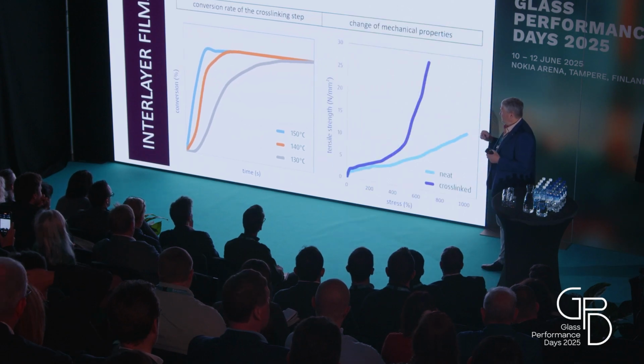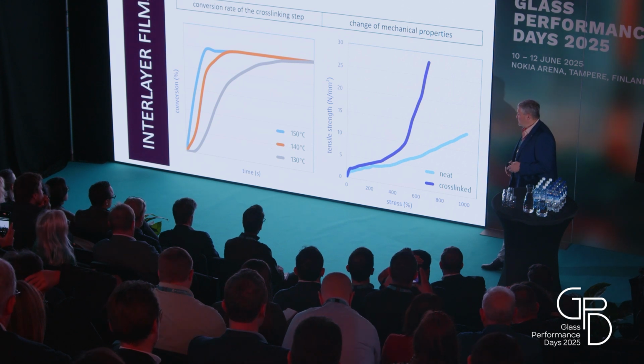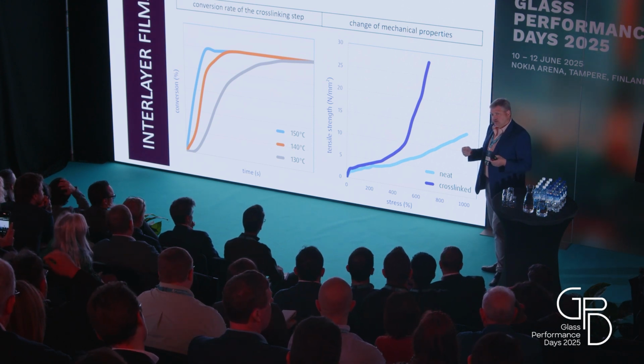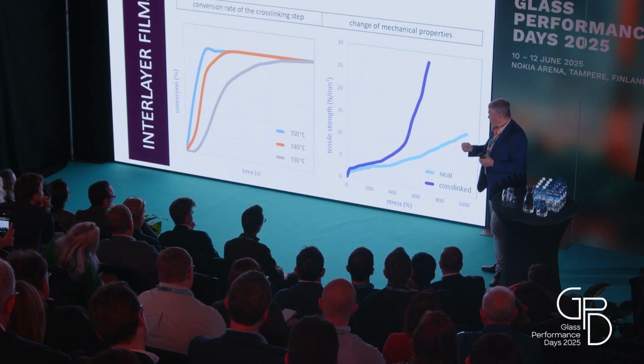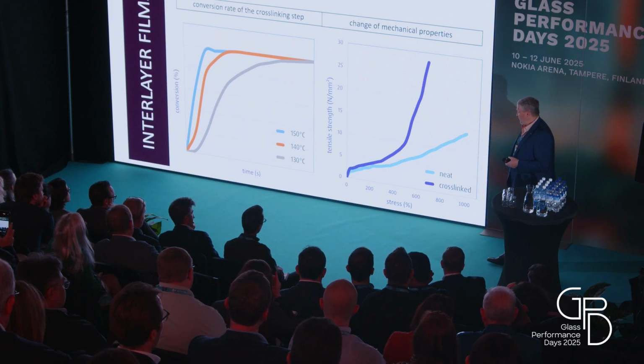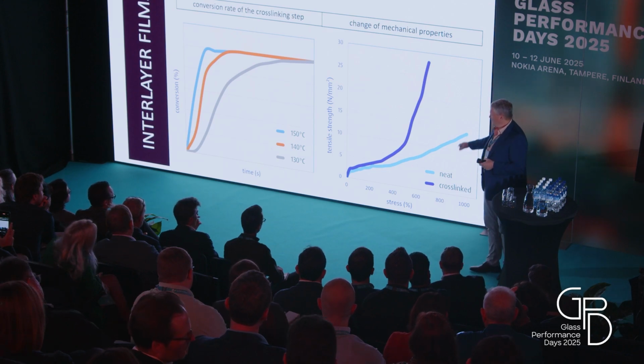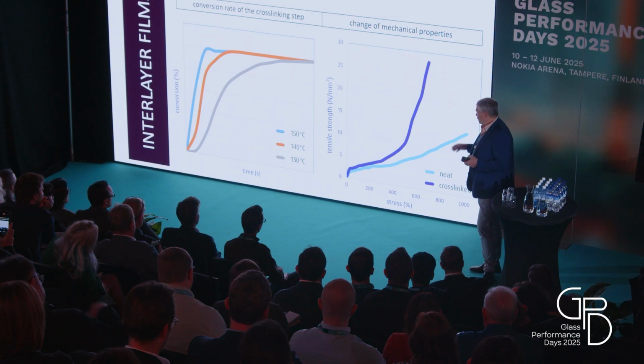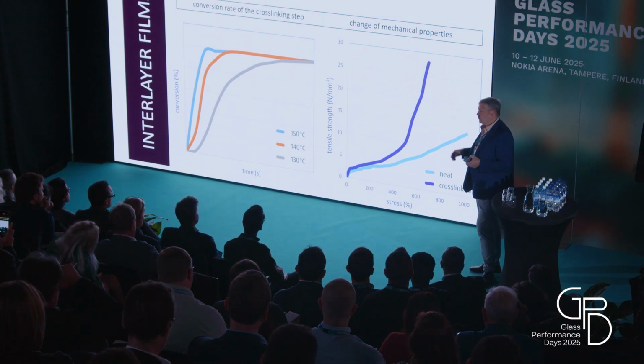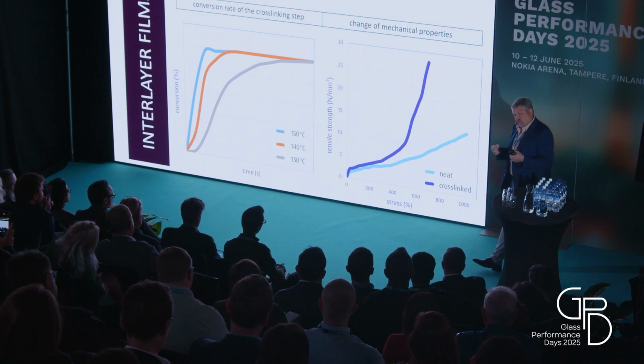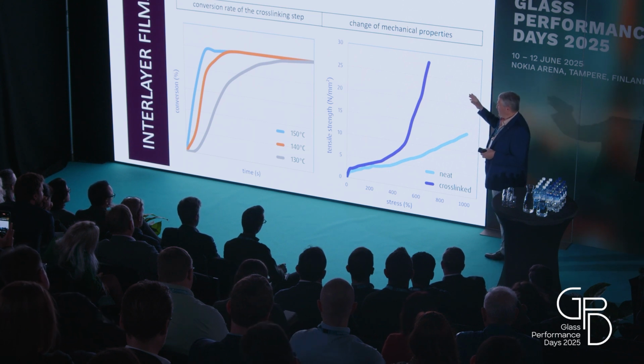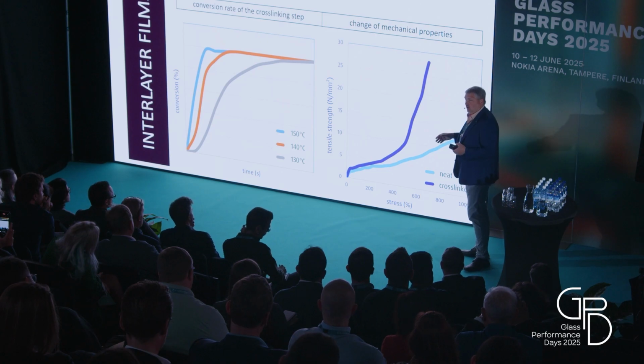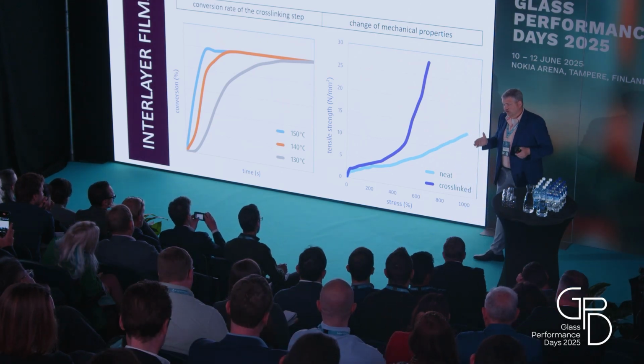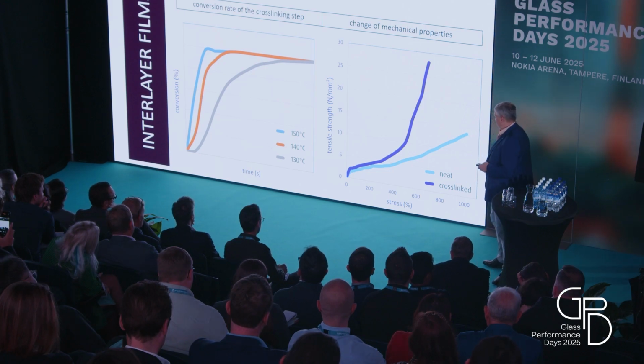And this cross-linking step is changing the material properties. Here you see the properties of the film. If you take a cross-linkable EVA interlayer in your hand, you can stretch it up to 10 times, means elongation rate of up to 1000% is possible. You need a certain strength, but okay, not so much. If you cross-link it, the material properties will change, the mechanical properties. You need much more force to stress it, and you cannot get to this elongation as it was before. Means we give, by cross-linking, much higher strength to the film. Of course, we reduce the elongation rate, but it's still at a level of more than 500%, which is more or less okay for the applications as we want to see.